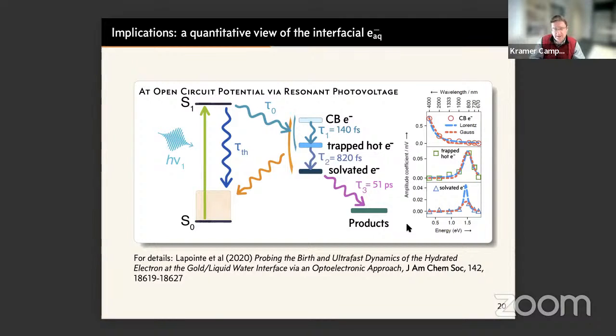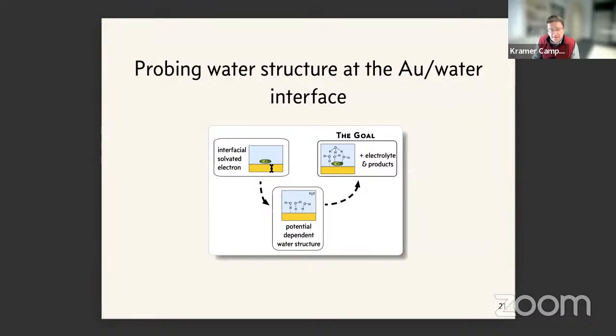The point here now is this is just a schematic of what we think is happening in the experiment. This excitation pulse creates a population of hot electrons, some of which relax in the metal directly, some of which are transferred either into the conduction band or into a kind of trapped hot electron state. This relaxes on a time scale of about 820 femtoseconds and forms the localized solvated electron, and on a time scale of, say, 50 picoseconds or so drives product formation. And of course, electrons can return to the metal without driving chemistry. Okay, so this is the solvated electron part.